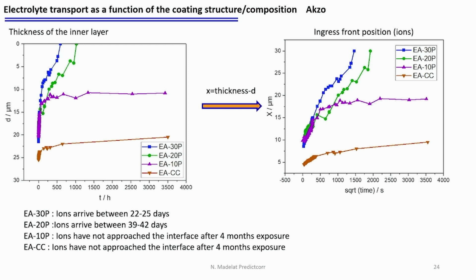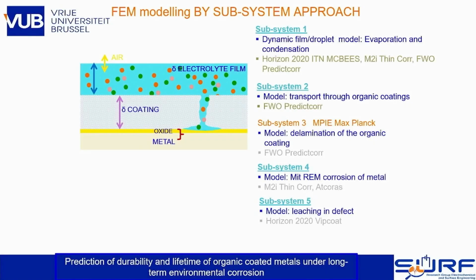the ions. So at the moment we are trying to match that with GDOES profiles to see to what extent we find back the ions in the depth profile. But you see, the mechanism allows you to see how the water is actually taken up by the coating, and what the transport of the ions is.